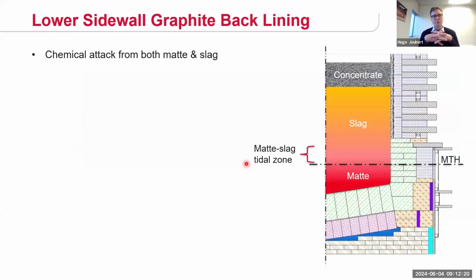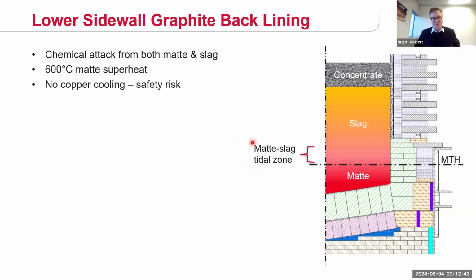So another important design change is on the lower sidewall area. Of course, this is a very critical area. We have both mat and slag in the tidal zone. Both the mat and slag in these furnaces are extremely aggressive to the magnesia-chrome bricks that we use, even if it's high-grade bricks. And as you probably know as well, we have a very high superheat of about 600 degrees Celsius in our mat. And in this lower sidewall area, we prefer not to have any water-cooled copper, just from a safety point of view.